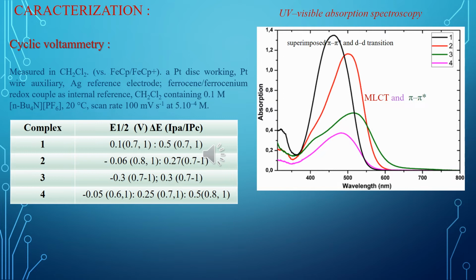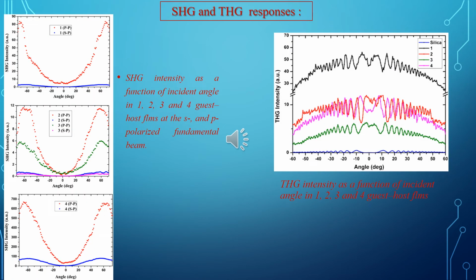In order to gain insight into the electronic environment of the metal atom in the new alkynyl complexes, the electrochemical properties of these compounds were measured by means of cyclic voltammetry. After the preparation of the thin films, we used the corona poling technique in order to orientate the chromophore at the thin layer surface. First, they were heated on a hot plate at selected poling temperature of 100 degrees Celsius. The measurement of